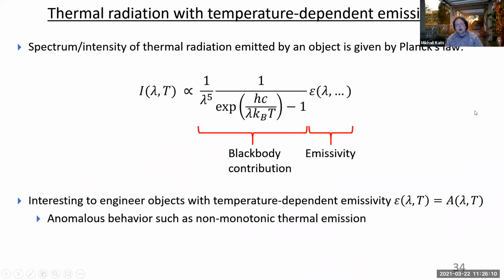So now let's talk a little bit about engineering, because I think that's interesting as well. I told you earlier that the emissivity can depend on many things, and it's very normal and common for the emissivity to depend on wavelength. This is something that we see all the time, but it can also depend on many other things. In particular, it's interesting to consider objects which have a temperature-dependent emissivity. And if we have an emissivity that is temperature dependent in a significantly strong enough way, you can get some anomalous behavior, like, for example, non-monotonic thermal emission.